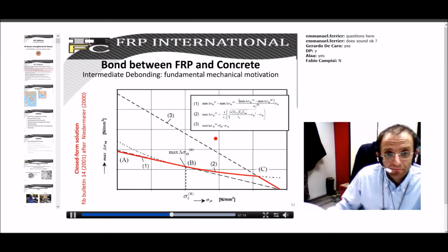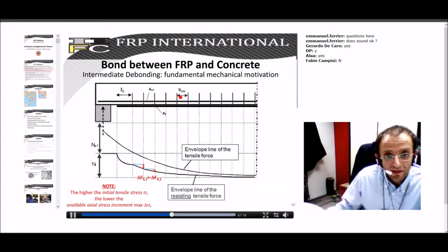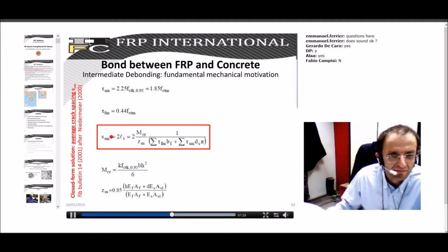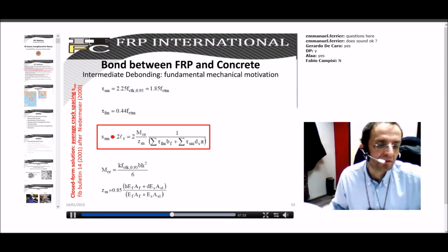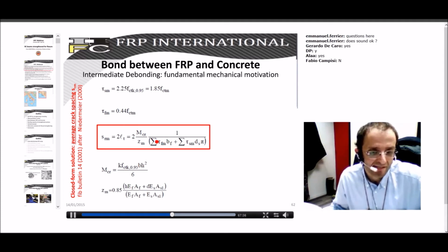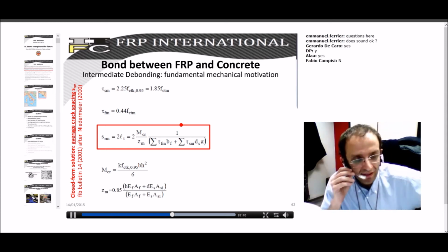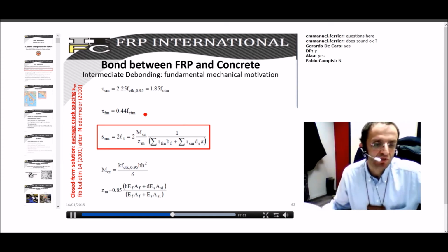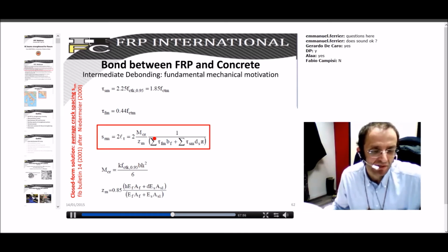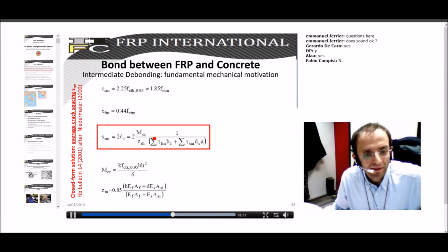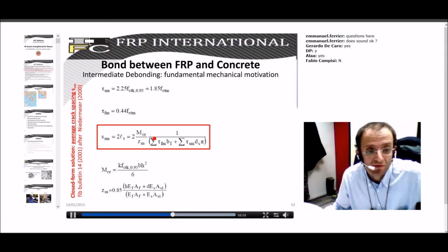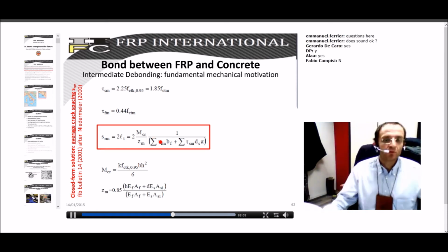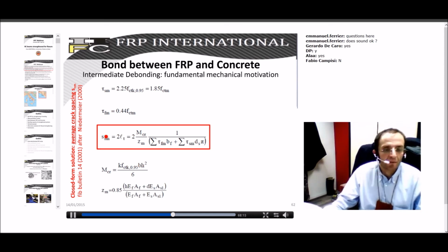Of course, as you see, the value of the distance of cracks is a very critical parameter which should be evaluated. In the literature, you find some relationships for evaluating this, taking into account both the external reinforcement and the internal one. As you know, for instance, from model code, the higher the amount of internal reinforcement, the closer the cracks. Actually, in my opinion, one should consider the cracks of the unreinforced member before the application of the FRP strip, because when you reinforce your member, usually the member is already cracked, so cracks are already formed. So it doesn't make sense, in my opinion, to take into account also the contribution of FRP.